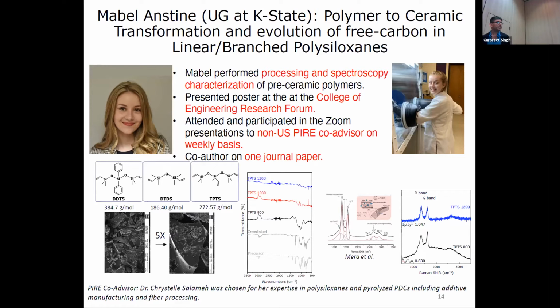which is very interesting, the majority of the mass loss occurs after cross-linking. So during the pyrolysis stages is when the majority of the mass loss is occurring. So we are able to cross-link these pre-ceramic polymers, and they solidify into white epoxy. But then the ceramic yield is negligible. Actually, in this case, it's less than 5-8%.